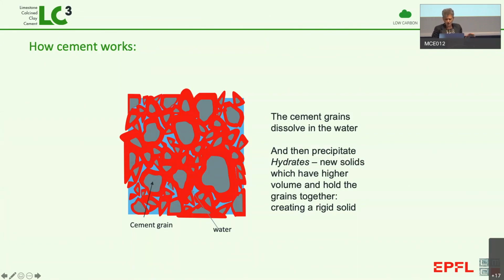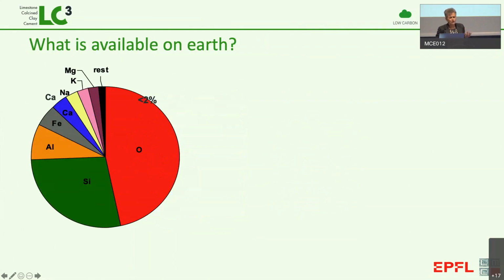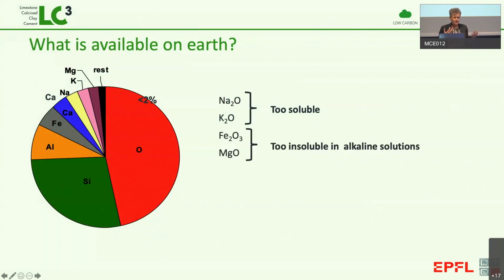So if we go back to this composition of the Earth and we look at the different oxides, what we find is that the oxides of sodium and potassium, they're too soluble. So they dissolve fine, but they don't deposit the hydrates. On the other hand, the oxides of magnesium and iron, here we have the opposite problem. They don't dissolve enough, so they just stay in the same place. So this means we go from the whole composition of the Earth to a system of just 3 oxides, which is the oxides of calcium, silicon, and aluminium.